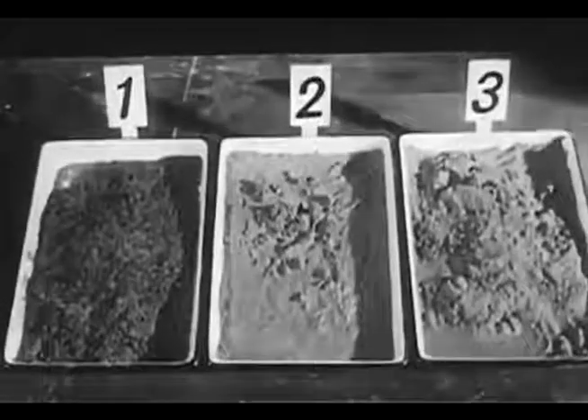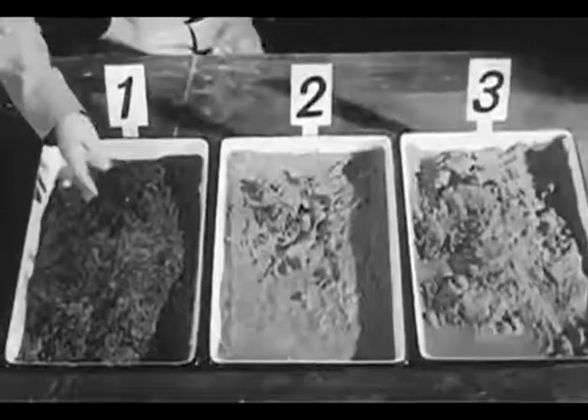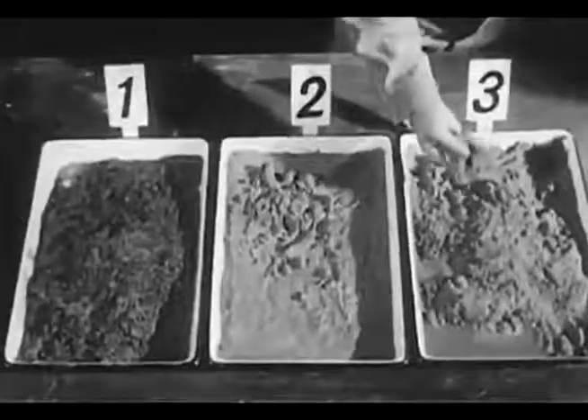This process separates the minerals from the waste and yields three products: first, a lead concentrate; second, a low-grade product called middlings, which is returned to the grinding circuit; and third, a product called tailings. Tailings and waste from the flotation machine are electrically pumped to the tailings pond.